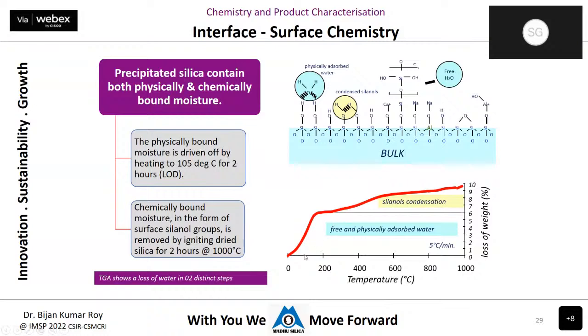If you look at the TGA graph, at 200 degrees and more, the chemically bound functional OH group is driven off. The moisture loss at lower temperature is only moisture attached to the surface, which can be easily removed, but not this water molecule. The surface of silica is surrounded by hydroxyl groups, and these hydroxyl groups have different positions, called vicinal, geminal, or isolated groups. Depending on the concentration of these hydroxyl groups, the functionality of silica in rubber plays a role. That can also be measured quantitatively: how much silanol group is there, and what fraction is geminal or isolated.